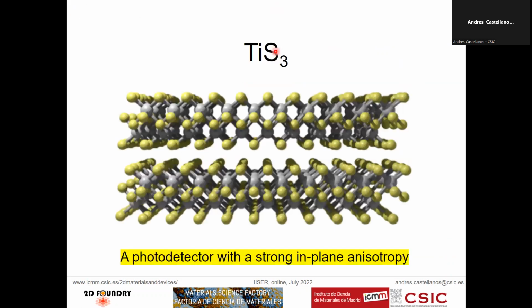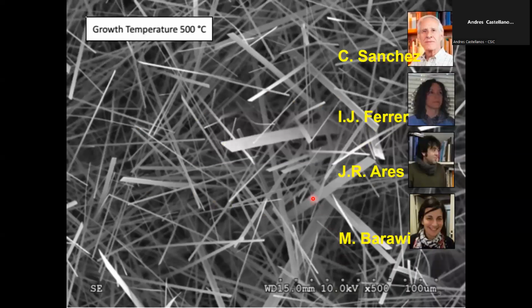The next material I want to briefly introduce is titanium trisulfide, because this titanium trisulfide opens up a brand new family, the transition metal trichalcogenides. Okay, so everyone in 2D optoelectronics is familiar with moly disulfide and transition metal dichalcogenides, but in this case, these are trichalcogenides. This is a family as large as the dichalcogenides, but rather unexplored so far. And what makes these materials different from the dichalcogenides is that they have a strong in-plane anisotropy. So this makes this material grow in these kinds of platelets.